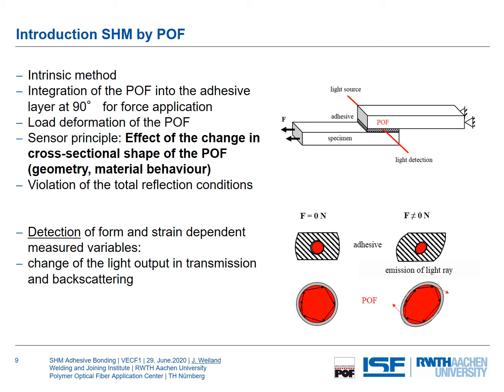We integrate those POF at 90 degrees compared to the applied force. The load of the single lap joint goes through the adhesive to the POF. Therefore, we have a change in the cross-sectional shape, and this changes on one side the geometry and on the other side the transmission behavior of the materials. In that case, we have a violation of the total reflection conditions, and therefore light rays go out of the POF, and the output and transmission will go down. And that's what we want to detect.